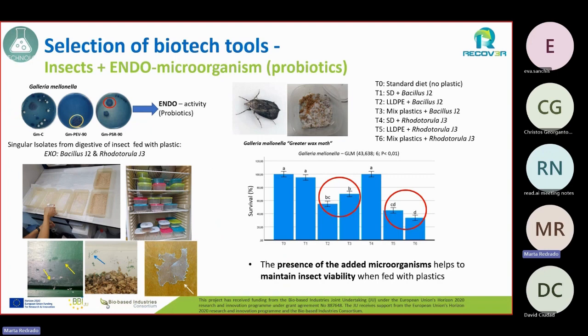First, the insects were tested on the different plastics, using a standard diet for the insect together with plastic in different forms, as a powder and also as a film. The insects prefer the standard diet, so they don't like the plastic much, but it was possible, as you've seen in the pictures at the bottom of the slide. They were biting the films, you see with the arrow, and they survive somewhat better on the standard diet, but the results with plastic were not that bad.